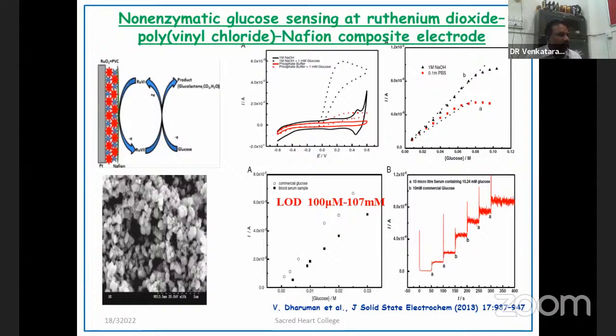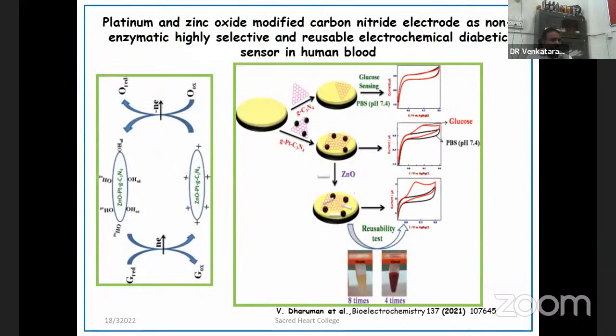We developed the device, but still we are not able to get 100% reproducibility. So we are still working with different materials. As we are also interested in using carbon material, here we use carbon nitride, on top of which we anchored platinum, because carbon nitride itself cannot sense glucose, and therefore we modify the carbon surface using platinum as well as zinc oxide. Why do we need to attach platinum and zinc oxide? To enhance the reusable behavior of the sensor.